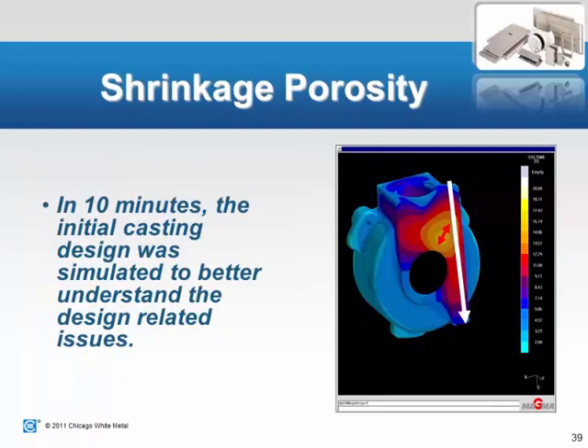During the first run, after about 10 minutes of the analysis, you can see there were some large, thick sections in this part. This is a solidification time chart. So you can see where this area that's red and yellow is going to take a lot longer to solidify in the tool than the blue and bluish green areas. Unfortunately, in this case, it is located right where the bore will go right through for the pressure tightness. So that was a problem.